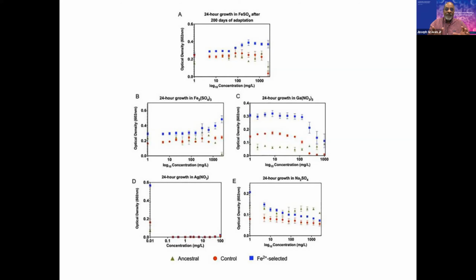So this is different from the ancestral population, which is taken directly from the sample of E. coli K12 MG1655 that we received from the company. So these are stored at -80. We bring them out, we let them grow for 24 hours, and then we assay them. So they're as close to that ancestral physiological state and genome as possible. The controls grow for the same number of generations as the iron 2 selected, but in the absence of excess iron.